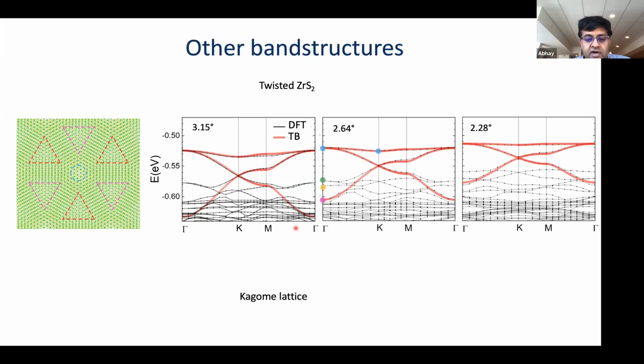And I'll give you a rapid fire 1 minute thing of what one can expect. One obvious thing is to ask what other kinds of band structures can you make by this kind of twisting? So here, this is a pure theoretical prediction for a material called zirconium disulfide. If you do the calculation for this, the simulated band structure looks very much like a Kagome band structure.